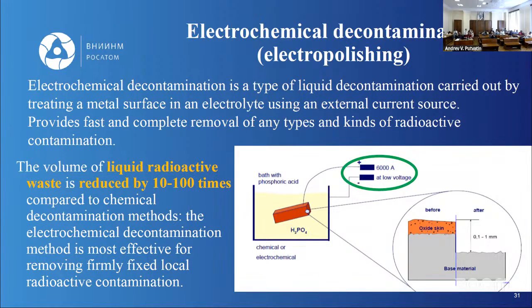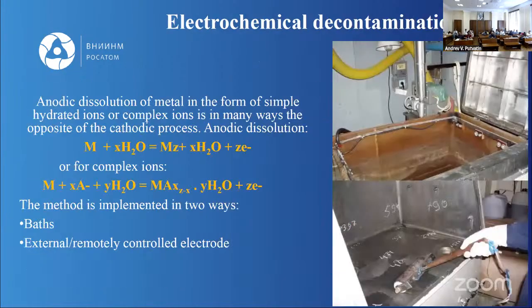With this method, we can remove from 100 microns up to 1 millimeter of the surface. This method can be applied in two ways: in the bath, and with an external electrode. You can just place your contaminated equipment in this bath and start the process, or you can apply an external electrode, like here, fitted with electricity, and then treat the surface of the materials.